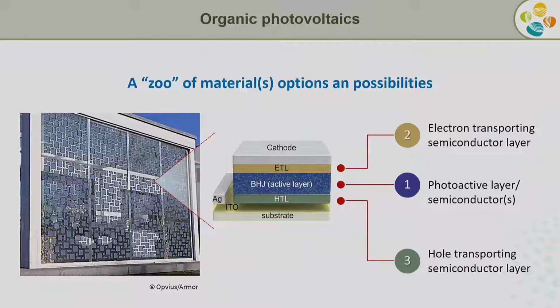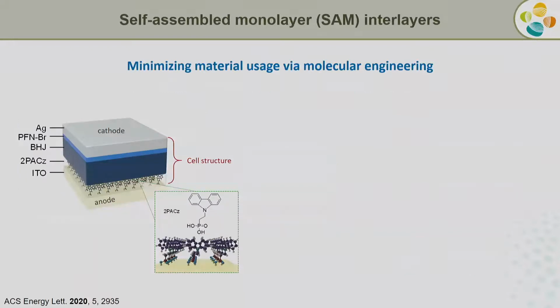So we've been working on improving the photoactive materials, but also improving the electron extracting and the hole extracting, the positive and the negative charges extracting layers, which play a very important role both for the manufacturing and the efficiency of the cells. So one important highlight from this topic is that we recently been able to use single monomolecular self-assembled layers. Like biology takes single atoms and builds us. In a way, we took single molecules which are engineered to functionalize, to essentially react with the surface of a specific electrode. And you essentially place the liquid there, and this molecule will self-assemble next to each other, forming very dense monolayers, which are only like a nanometer thick.